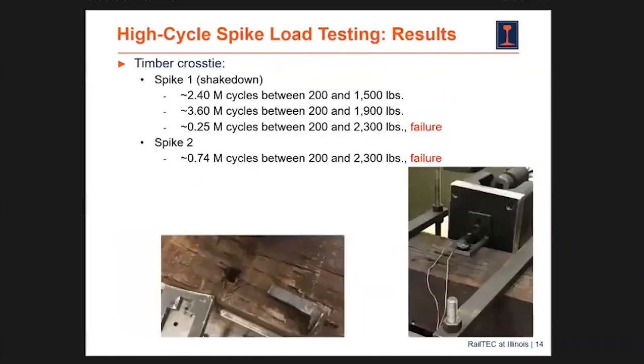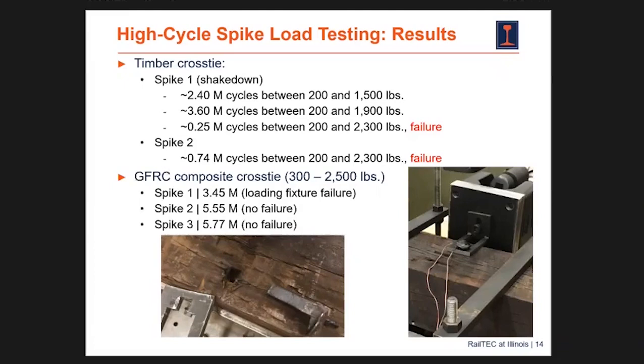And whenever we look at our results from our timber cross ties, the first rounds of shakedown with the timber tie, we were trying to figure out what load magnitude is going to create failure in a reasonable number of cycles. And so we landed on going right up to about 2,300 pounds, cycling from 200 to 2,300, and we got failure. We ran this again and got failure in less than 1 million cycles. And so one, we were able to reproduce the failure, and two, we were able to do it in a reasonable number of cycles.